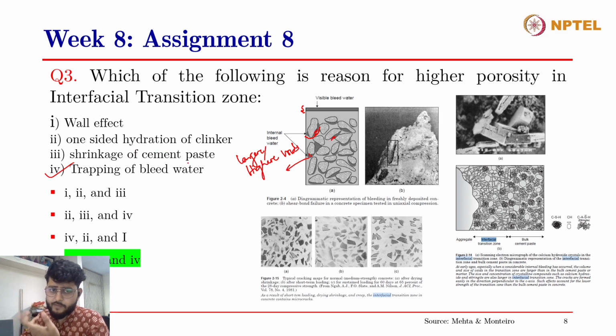Then we have already discussed shrinkage of cement paste. All right, let's first discuss all these view graphs, then we'll come to that. I was talking about the second view graph, where you see that at the boundary of the aggregates and cement paste, since the ITZ has a higher porosity and a higher unoccupied volume, the water that is present as a film around these aggregates contains calcium, sulfate and aluminum ions, right? And due to higher space availability around the aggregate boundaries, the ettringite, CSH, and calcium hydroxide particles are much larger. So the volume occupied by these hydrates is larger than that present in the cement paste in the core, right? You can see over here.